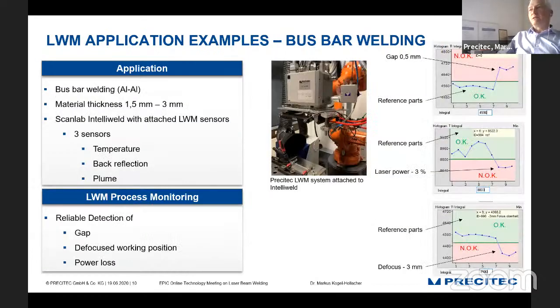Another application is busbar welding. What you see here is more or less a little bit underneath the surface of the laser welding monitor, where we have a lot of statistics, and you see here typically three typical problems which can occur in these applications. It's a gap between the sheets. It's a laser power drop, which can occur, for example, which was mentioned before, because of contaminated protection glasses, or a defocusing, which is happening because of misalignment of the part.